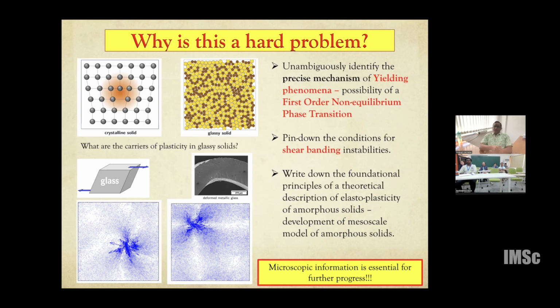And so there is significant progress made along that line, which suggests that these STZs, if they line up, basically produce shear bands, and that leads to crack formation. And it has been shown via energy considerations that STZs lining up is an energy-minimized configuration. This is the work done by one of my collaborators from IIT Bombay, Atul Dasgupta, with Itamar Procaccia, my former postdoc advisor.